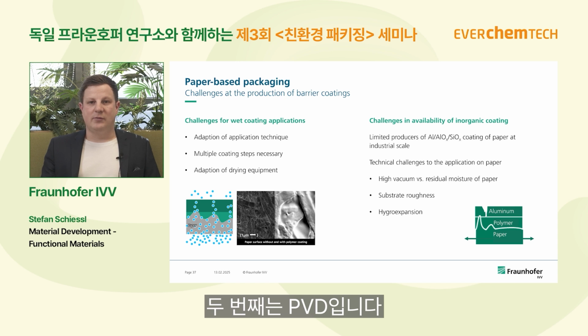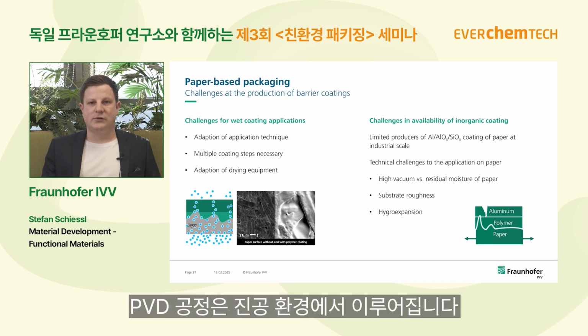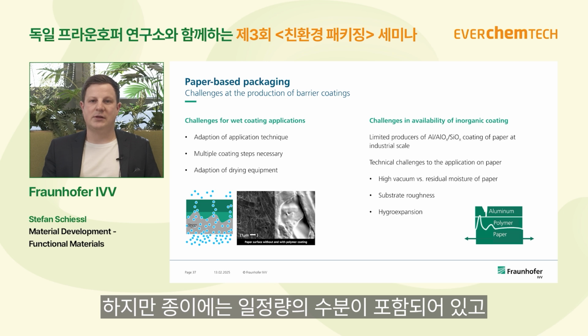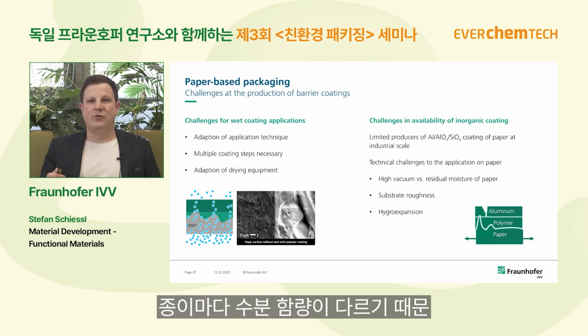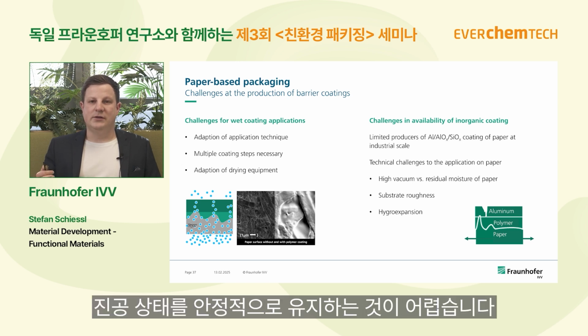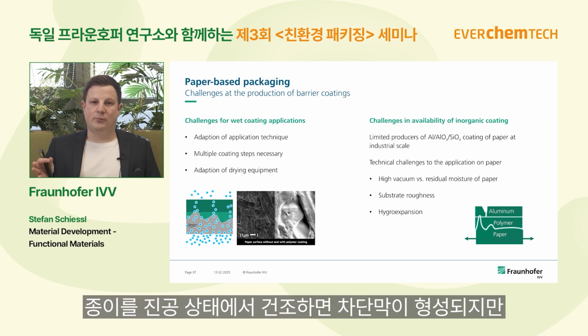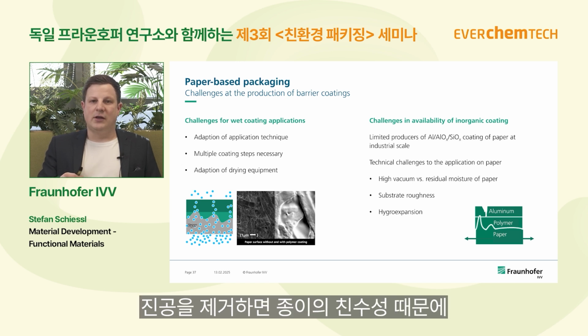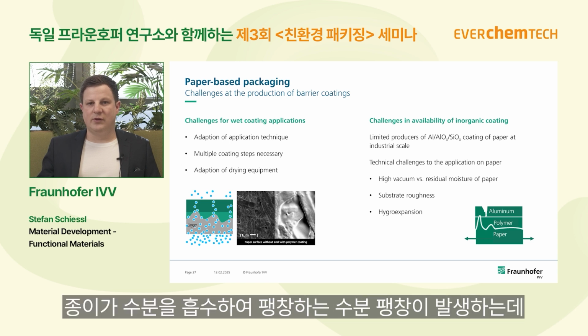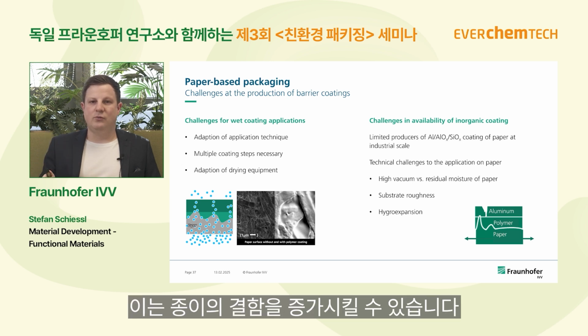When we are talking about physical vapor deposition, then the whole process is happening at vacuum, and paper contains some amount of water, and since the water in every paper is different, also the stabilization of the vacuum is not very easy during the process. And if we put the paper into the vacuum and it is dried, then we build up the barrier layer, and after removing the vacuum, the paper is again, because of its hydrophilic nature, taking up some water, leading to an expansion, which is called hygroexpansion, and this might lead to the fact that we increase the number of defects just after removing the paper to a humid environment.